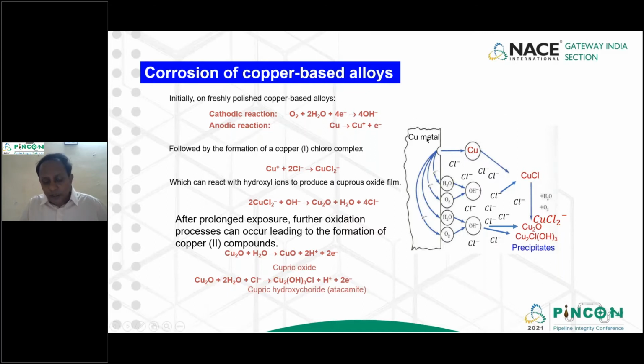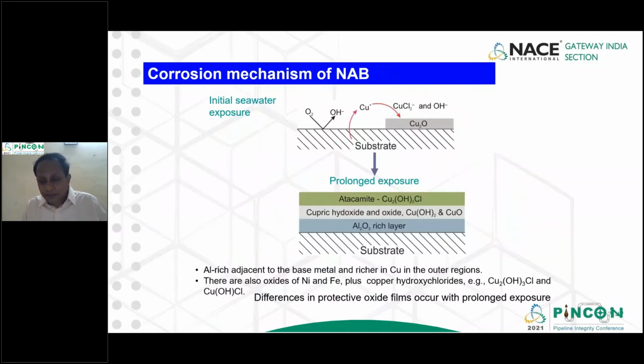But here I have a base copper metal, and if you see here, that is our classical anodic reaction. The electrons are released from the copper, and it reacts with the oxygen and water which is in the bulk media, and it forms a cuprous ion, and the cuprous ion can react with the chloride complex to form a cuprous chloro complex. Then it forms a lot of precipitates, the green color precipitates. You end up having atacamite. But all these phenomena we see when there is a static environment. But the moment we go into flow condition, that changes, which we'll see. But here the other one was pure copper.